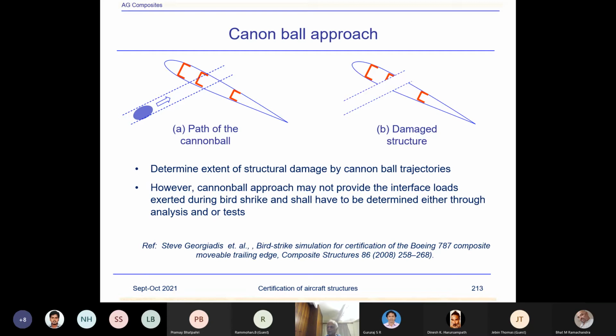So what you will do in practice, depending upon the probabilities of the angle at which the bird can hit the structure, at various incidences of the angle of attack and bird strike path, simulation will be done. How much structure could be damaged? Suppose the bird hits with a greater impact, it just takes away all this material. So this is what the cannonball approach is: we simulate, in the known path for different parts of the bird, the removal of structure, or the damage created like a cannonball. And then the remaining structure will be analyzed by finite element methods.